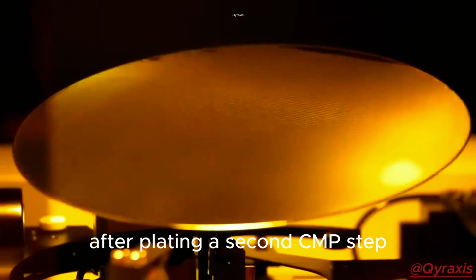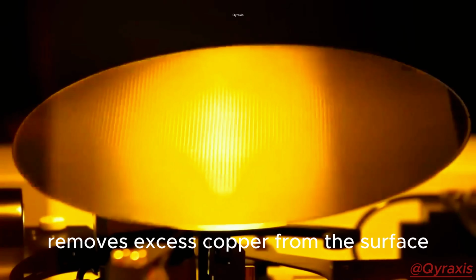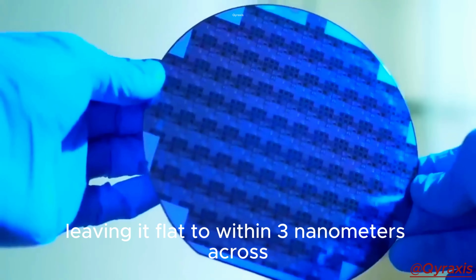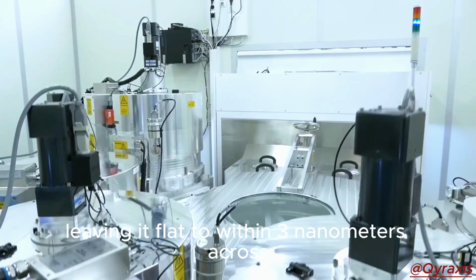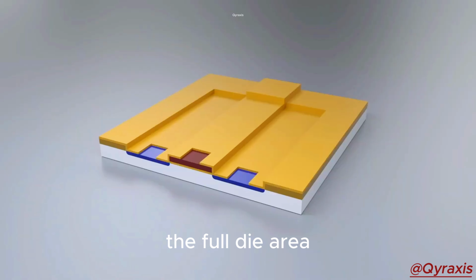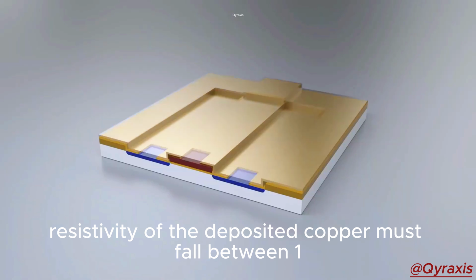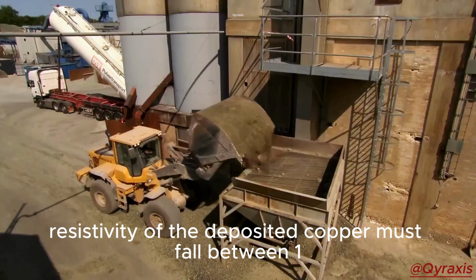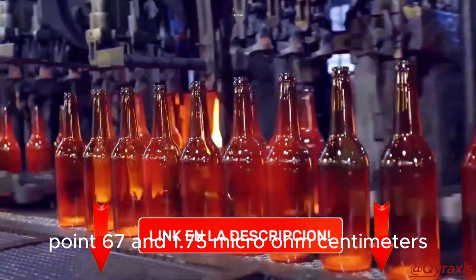After plating, a second CMP step removes excess copper from the surface, leaving it flat to within 3 nanometers across the full die area. Resistivity of the deposited copper must fall between 1.67 and 1.75 micro-ohm centimeters. The tolerance window is less than 5%.